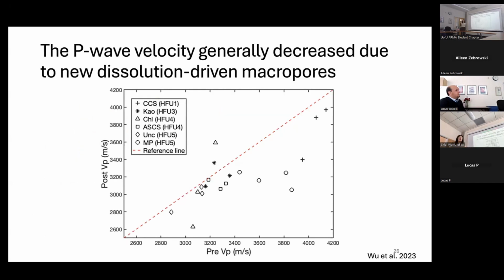P wave velocity. Yeah, this is another. So we're now shifting to more mechanical observations. P wave velocity, as we mentioned before, is a dynamic measurement. Here, we generally see P wave velocity decreased during the CO2 injection. Most of the points are in the lower region of the plot. So it means pre is larger than post, which makes sense. Well, there's some dissolution happening.